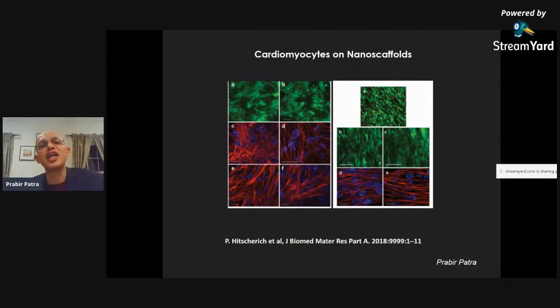So we started studying cardiomyocyte cells, which are the heart cells, on these scaffolds, and we saw very nice sarcomeres formed. Wonderful heart cells follow a particular scaffold that has an electrical gradient. A heart cell is different than a skin cell, so you have to do something onto the surface of the electrospun fiber that we made. So what we did instead is make a combination of PCL and graphene. Graphene is conductive, PCL is not. So it has conductive, non-conductive, conductive, non-conductive interfaces that create electrical potential. Somewhere conductivity is high, somewhere low, somewhere medium, somewhere low, like that.